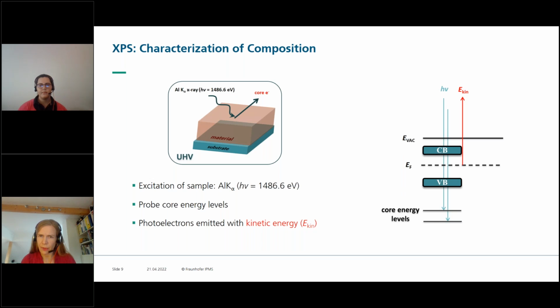And the first question was if it's possible to force an electron to get removed from the core levels. So it depends on the energy of our incoming beam. For a given X-ray beam, when you excite your sample, you eject core energy electrons, and this electron is emitted with a given kinetic energy as it exits your sample into vacuum, and this electron energy is caught by your analyzer, and therefore you can back calculate the binding energy of your electron.